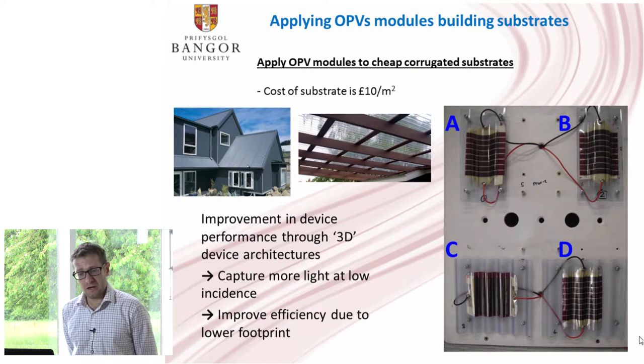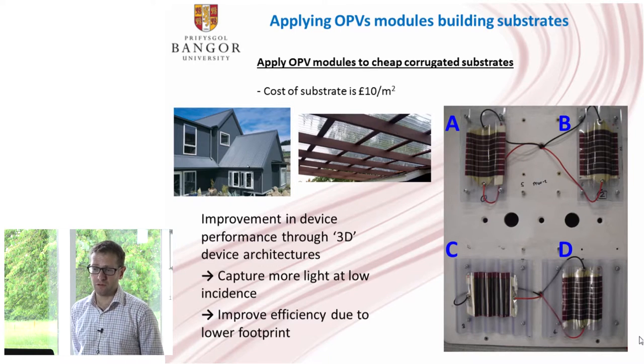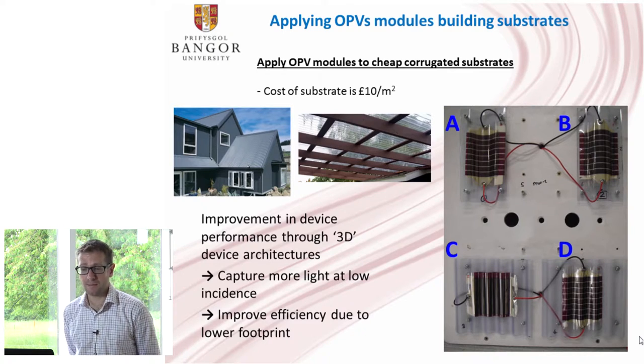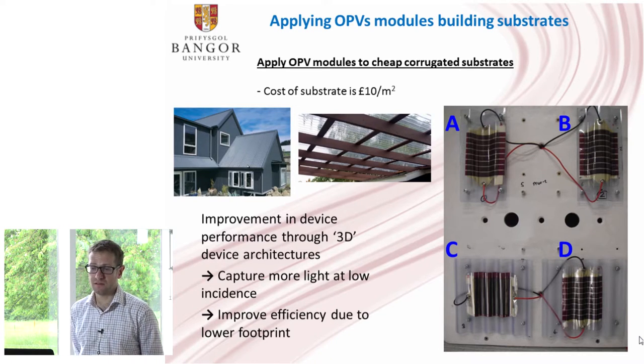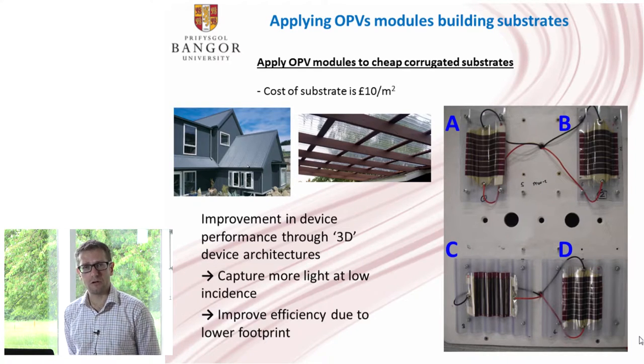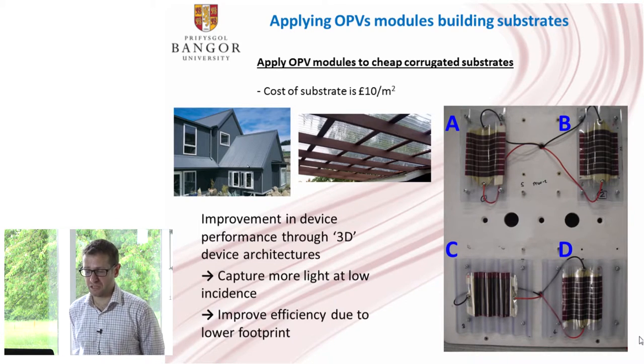Moving on, I'm going to talk about some of our other work, where we've been looking at applying organic solar cells onto existing building material, laminating them onto, well, not flexible, but three-dimensional substrates. The idea is we use a very low-cost substrate, typically costing around 10 to 15 euros per square meter. By using a three-dimensional architecture, we're able to capture more light at a low angle of incidence, and we can also improve the efficiency of our solar cell by reducing its footprint.